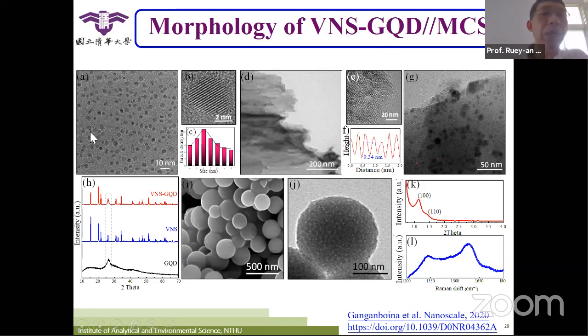This one actually is the case with the VNS and graphene quantum dots, the upper part here. The lower part is another case. We call this one the MCS, mesoporous carbon sphere, so we can see the sphere here. And then from the TEM, we can see they have some light spots here. This one is their pore here. And here we can see the low-angle XRD, and they are quite good.